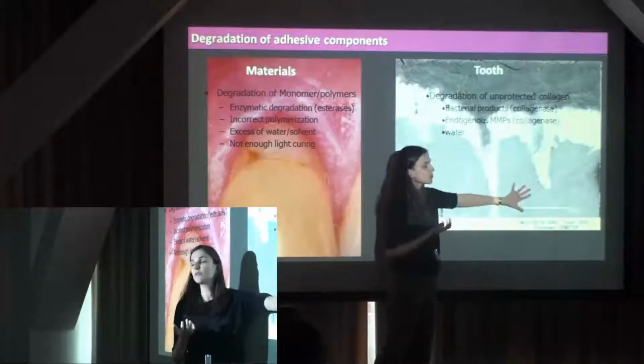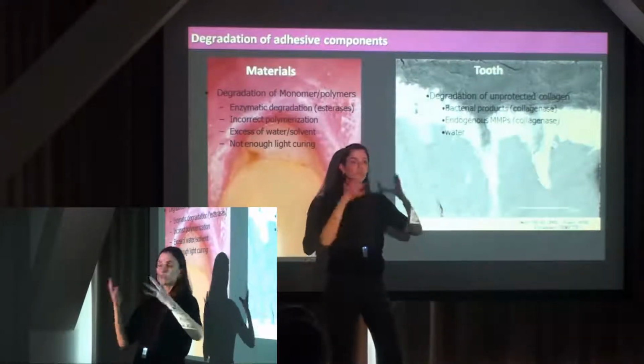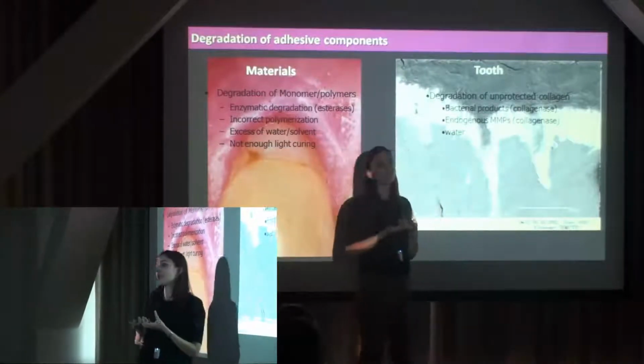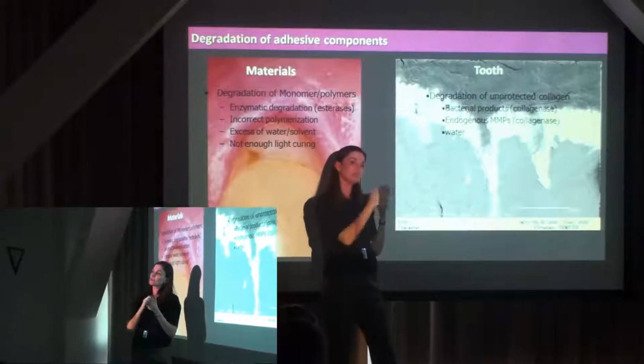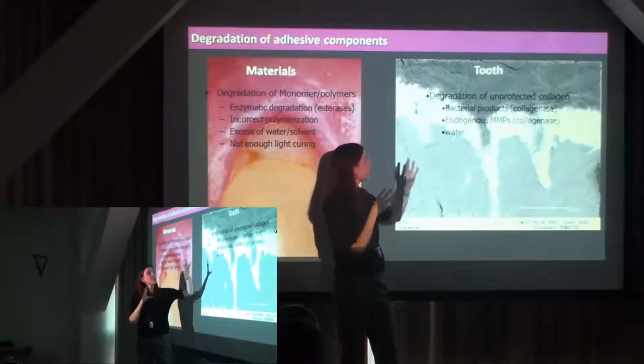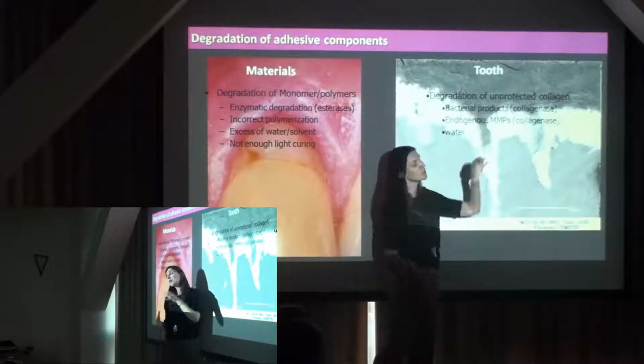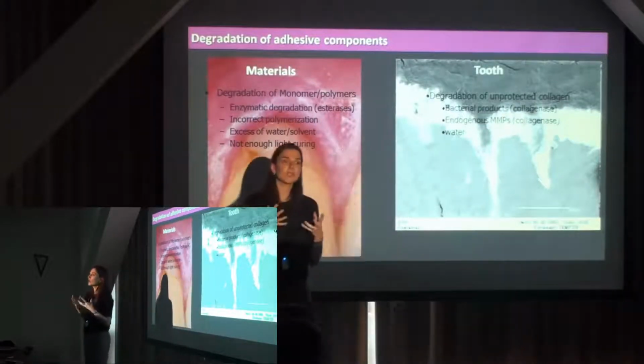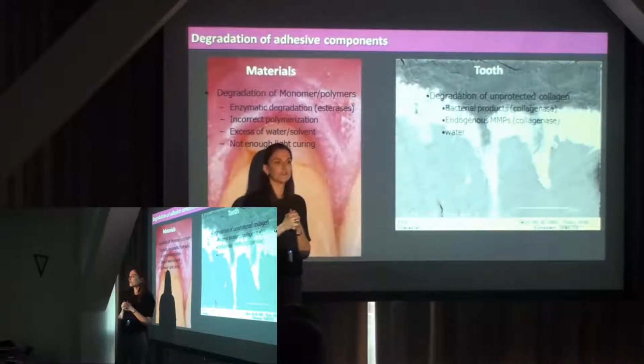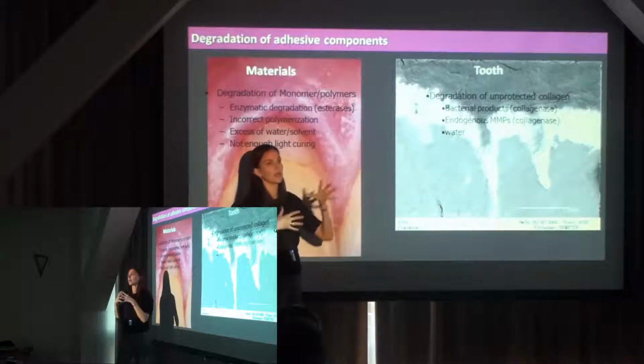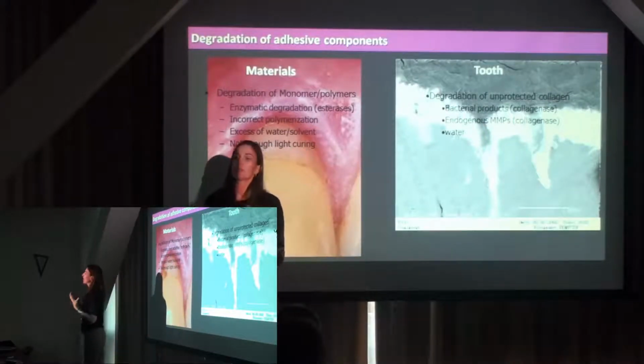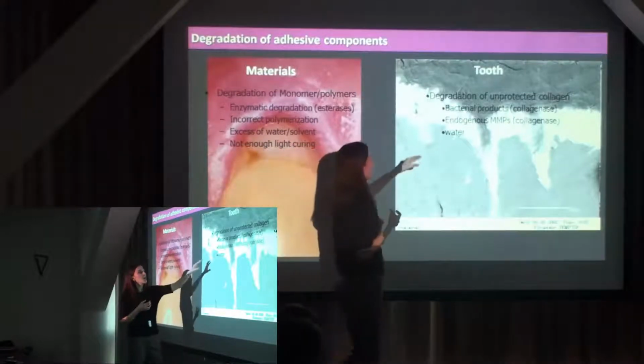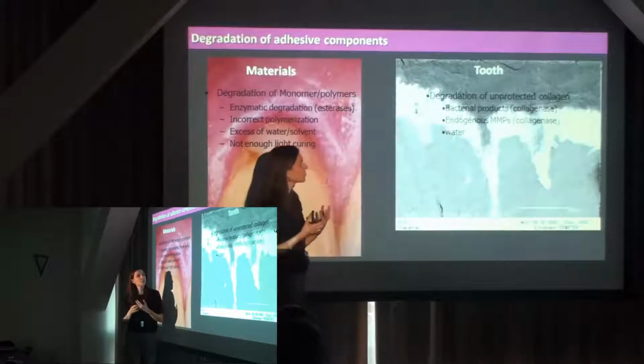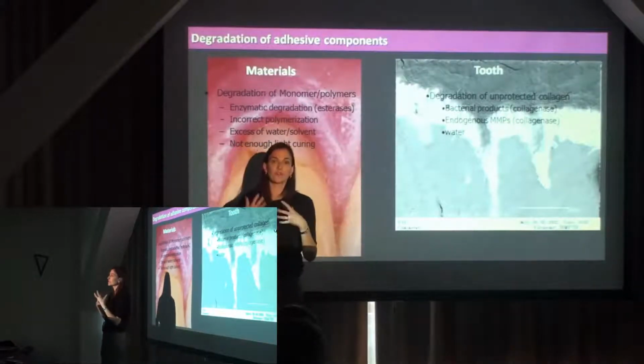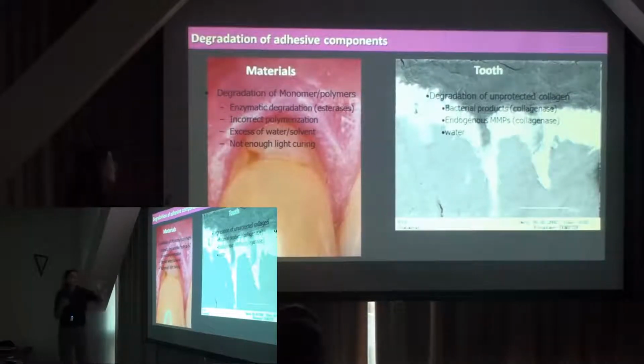So these enzymes are in the tooth itself as part of the mineralization process when this tooth is formed, and they're also available in the environment, right? And so if there's any opportunity that they would ever go into that interface from the oral environment, they could help in this process. There are also some collagenase that's released by bacteria, but those are kind of limited to very deep pockets into the tooth where specific bacteria do release that. Bacteria that cause decay, primarily they release acids, and that's how they decalcify the tooth. We also have water there that can also increase susceptibility of collagen degradation if this collagen was somehow weakened through the process. So basically, we have to deal with these two issues.